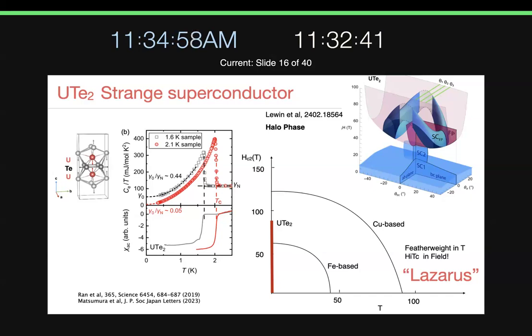In all of these directions, you've got major questions. For example, this is obviously not paramagnetically limited. It's obviously orbitally limited. But at 80 Tesla, you have to have an extremely short coherence length. That's such a high upper critical field. How can you have such a short coherence length with a 2 Kelvin superconductor? This is a system which, if you look at the numbers, would have a coherence length comparable with a cuprate superconductor, even though it has a TC of about 2 Kelvin.